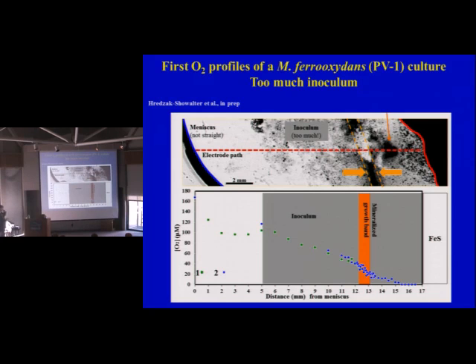And as you can see, we did 2 different experiments with a microelectrode at 2 different spots, and you can see that we get very good reproducibility between the two. Okay? So it says to us, at least we're setting up gradients much like we would do with gel tubes or other types of systems in general.